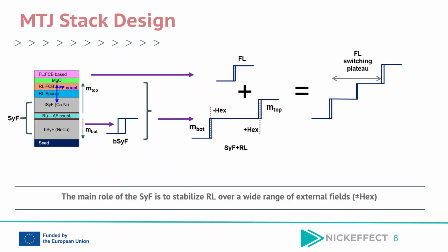In a well-designed MTJ stack, the top part of the SyF, tSyF, is ferromagnetically coupled to the reference layer, RL, through the RL spacer in order to stabilize the RL switching behavior and create a well-defined free-layer switching plateau between -HX and +HX, as shown in the center switching schematic.